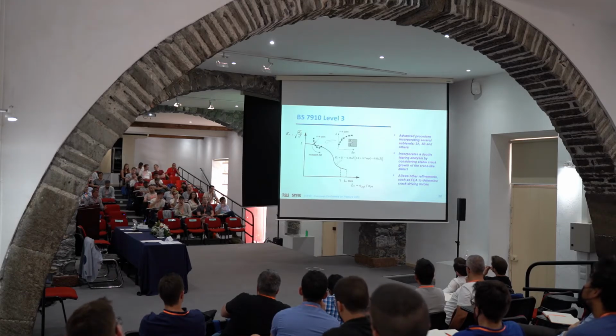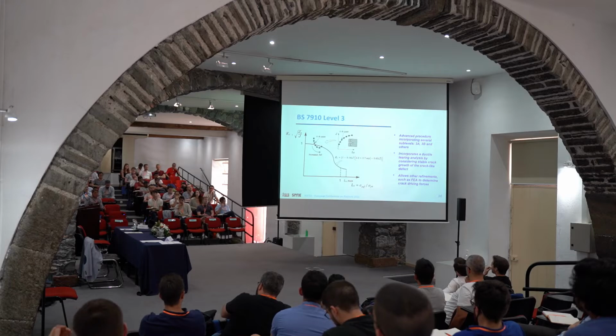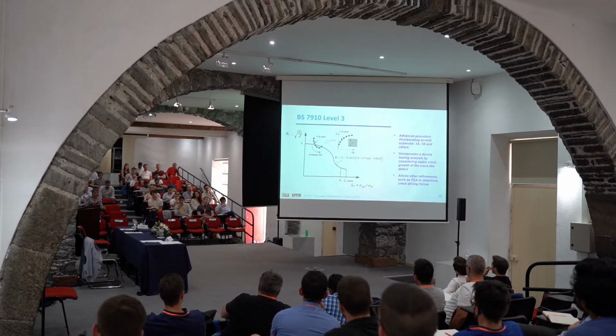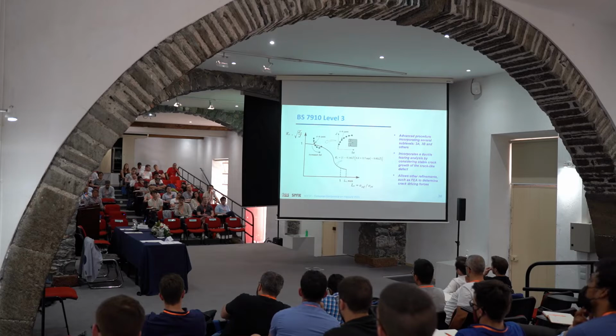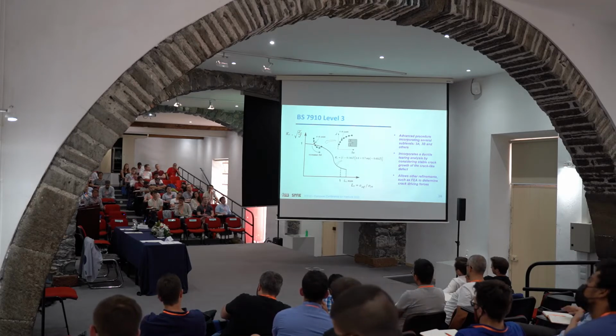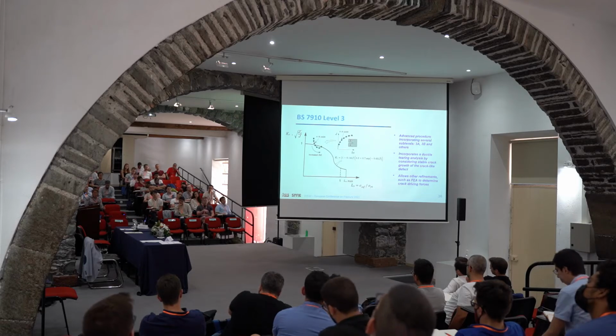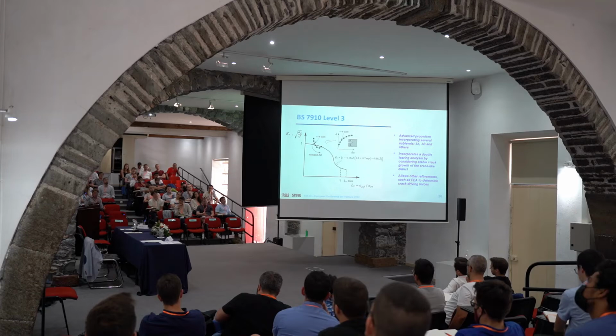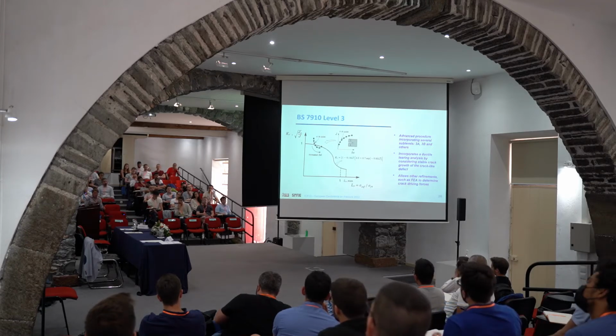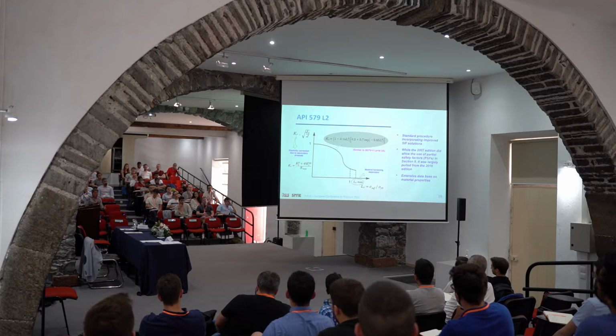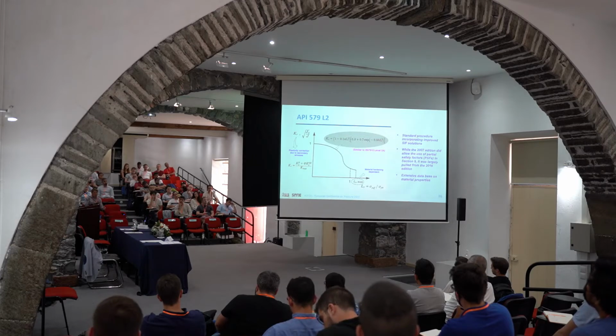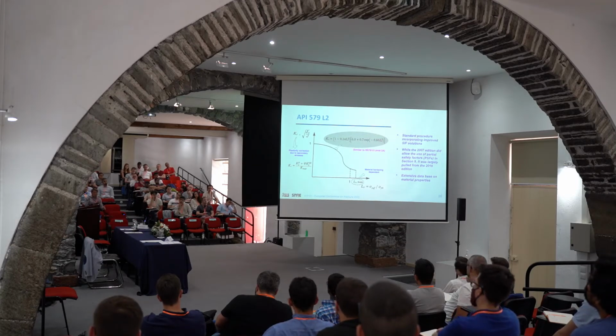Okay? The stress intensity factor solutions incorporated in the British Standard procedure rely on a very simple calculation of the stress intensity factor for curved pipes, for example. Okay? So we usually get an analytical solution for a flat plate and just consider the curvature. Therefore, it's an approximate solution. It's a good solution, it's approximate. In API 579, all the solutions incorporated into the procedure are based on finite element analysis. So they are very accurate, very.